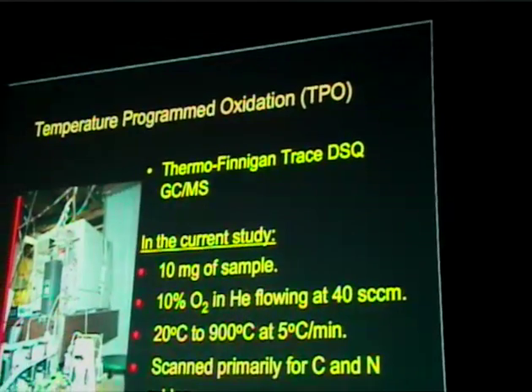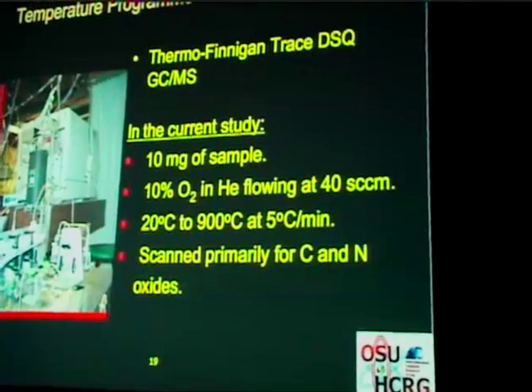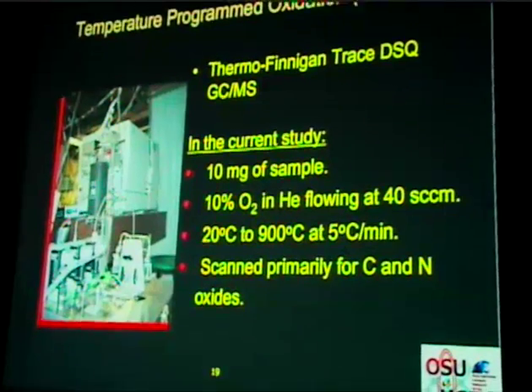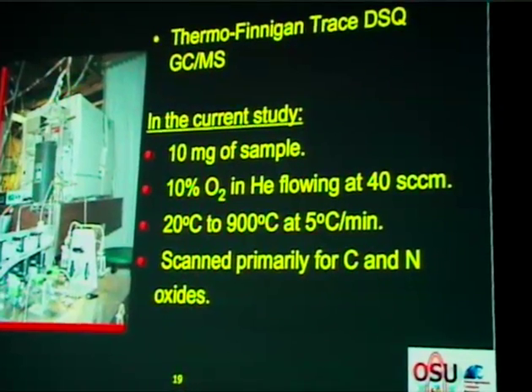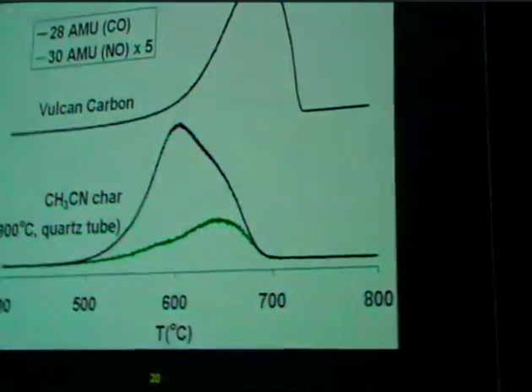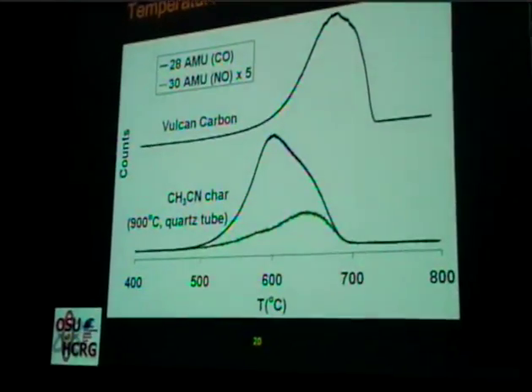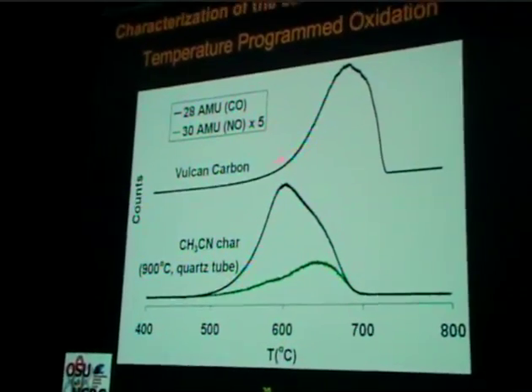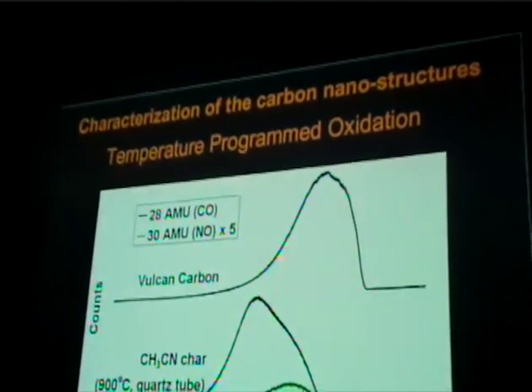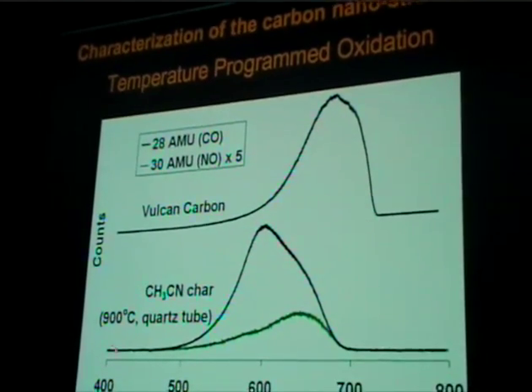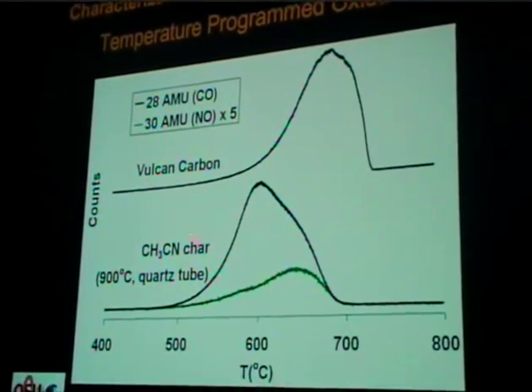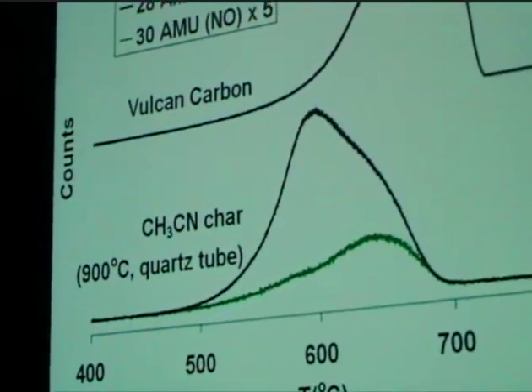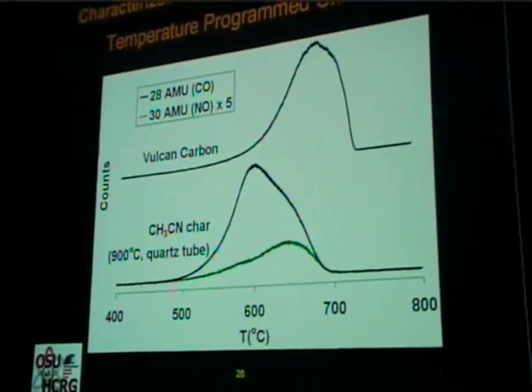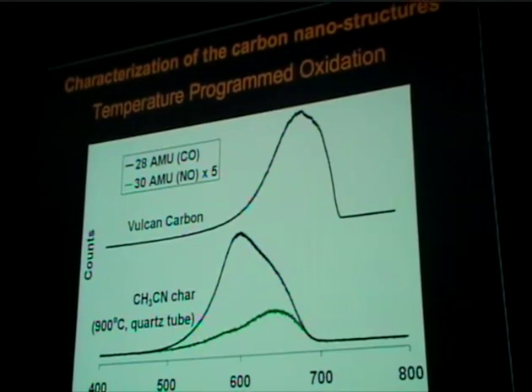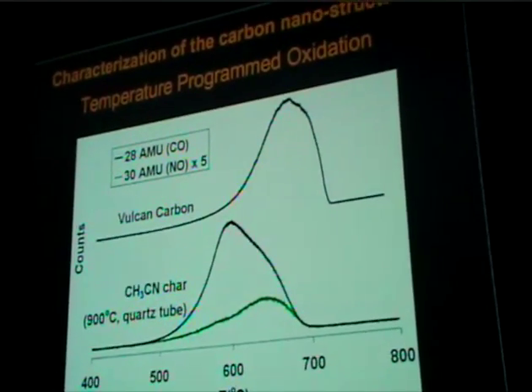Now, we looked at the oxidation behavior of these materials, how easily these materials get oxidized. Again, we are using a GCMS combined with a TGA system. And if we look at the effluent from the temperature programmed oxidation experiment, here's the Vulcan carbon. The oxidation is starting around 600 degrees centigrade. And here are the carbon structures which are grown as a result of the acetonitrile pyrolysis. And as you can see, the oxidation starts much earlier. So whatever we have in these materials clearly is catalyzing the oxidation of carbon.